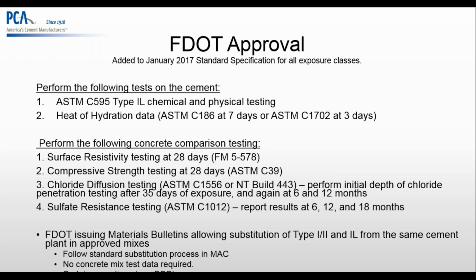As far as the cement companies, they have to provide an extensive battery of testing. As far as the chemistry of the cement, the physical aspect, all the testing has to be provided, the heat of hydration as well, but also concrete testing has to be done, and this is by a third party, right? You can do all the testing that you want internally, but you have to provide testing performed by a third party of their choice that has to be approved, right? So the surface resistivity at 28 days, the compressive strength, of course, and the 3.3 and 4 are the durability, the chloride diffusion testing, and the sulfate resistance testing, also the C1012. That has to be performed, and the results have to be provided to the FDOT with successful testing in order for the PLCs to be approved in any FDOT project, right?